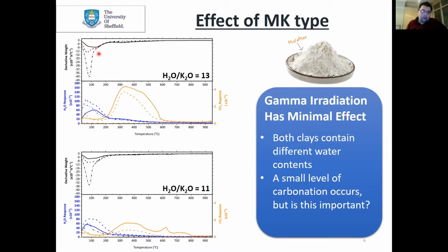This is what we call bound water, held within the gel structure of the samples. When it's been irradiated, if we start to see a loss of this water, you really want to consider what is happening to the structure, as structural changes may be occurring. That is what we see here for this lower water content system.